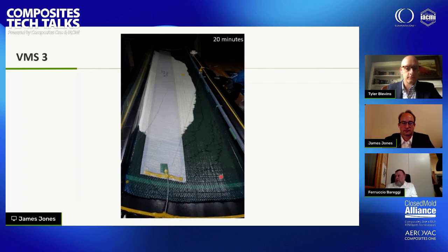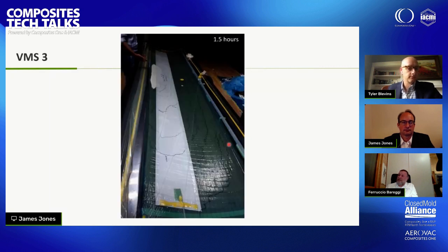As you can see, the flow front has this peculiar shape, quite rounded. This is due to the fact that the part is, as I was saying, very thick at the center, and it is tapered at the end. So the thickness is diminishing at the ends and is going down to one layer. So where the layers are less and the content of glass is lighter, the resin impregnation is faster. So that's why you have this faster flow. But as you can see, at the end of the process, the part is, in this case, almost completed, and it will be totally completed, as you can see in the next picture, the next slide.